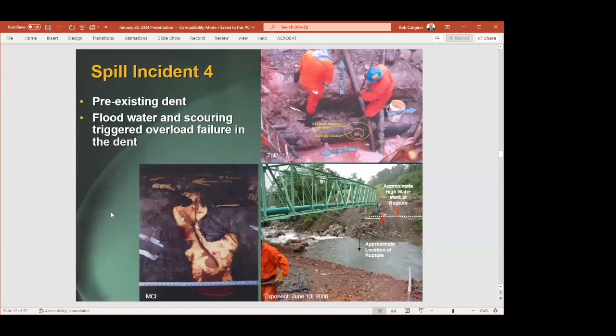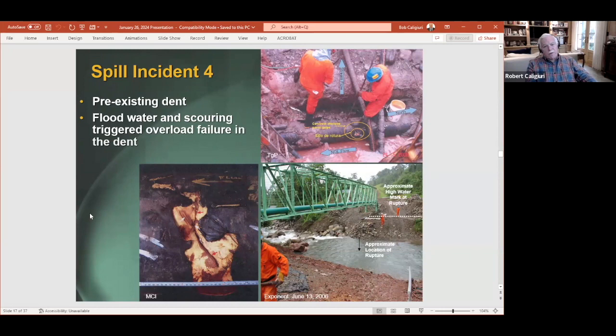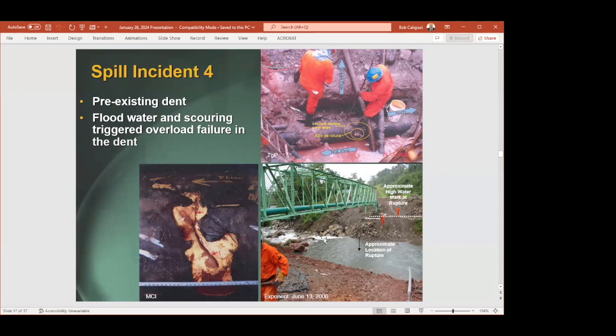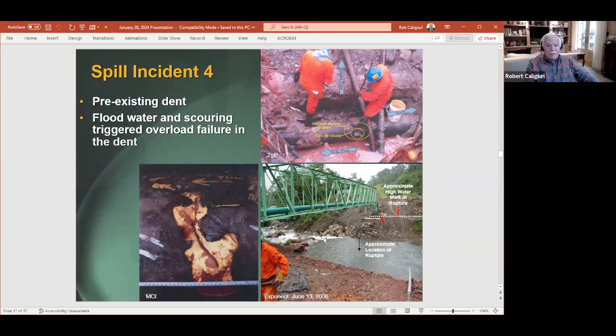This one's different. This is a crossing of a river, and what happened here, there was a pre-existing dent in the pipeline, and the floodwater, which is pretty common in the Amazon, triggered an overload failure. And I have seen this before in other pipeline systems, where if there's some problem with the pipeline, the moving water can actually introduce an overload failure in the piping, and that's what happened here. It was under the water, but it failed.